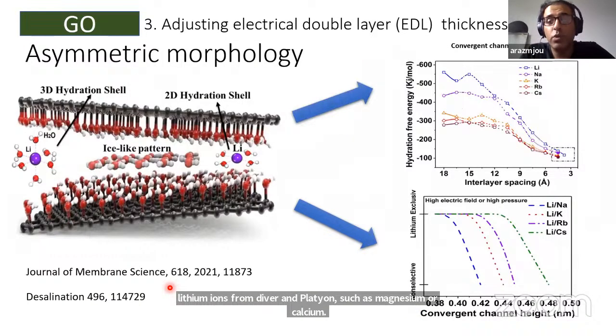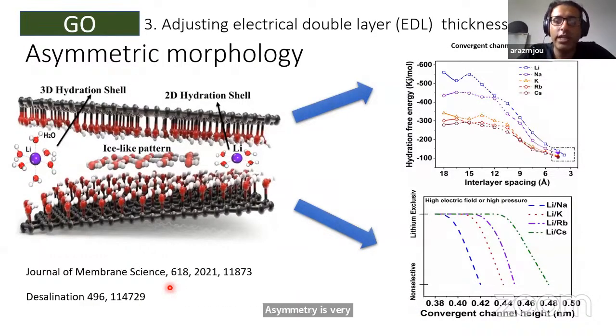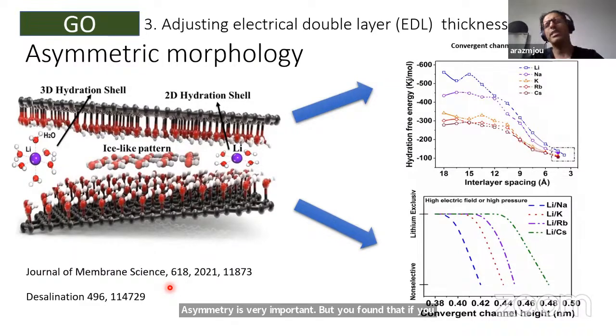Asymmetry is very important, but we found that if you can create some asymmetry within the nanochannels of graphene oxide, basically any 2D nanostructure, you can turn a non-selective membrane into a lithium exclusive membrane.